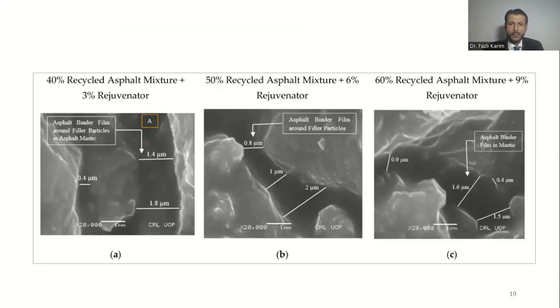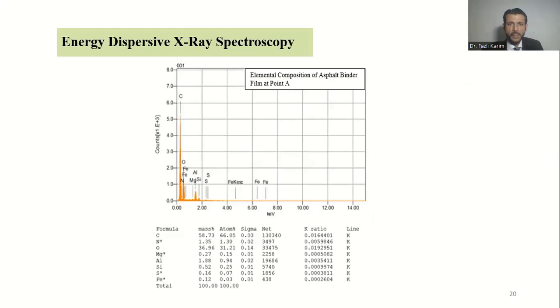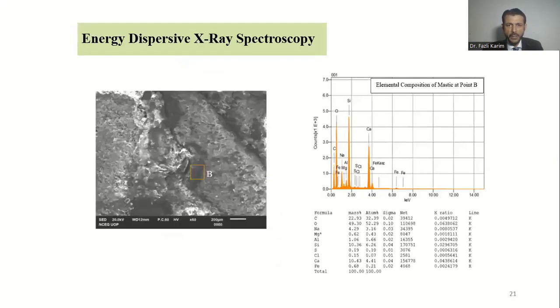And similarly, here a point A was selected so that EDS can be conducted in order to detect the presence of pure binder film, just like the conventional texture. This is the elemental composition of asphalt binder film at point A, which guaranteed the existence of pure binder film. Similarly, a point of asphalt mastic was also chosen at point B, and EDS was conducted. All the elements in the configuration reveal the existence of pure asphalt mastic.